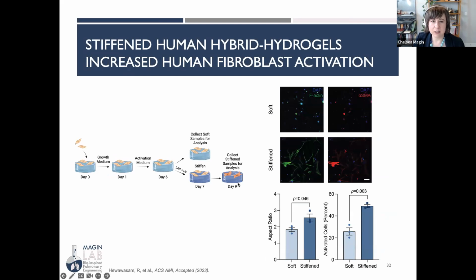So you can see in the stiffened human hybrid hydrogels, human fibroblast activation increased on the stiffened microenvironments. You can see here in staining for F-actin and alpha smooth muscle actin, and also quantified below. The cells increased in aspect ratio when we stiffened the microenvironments, and also increased in activation or expression of that alpha smooth muscle actin. So we're excited. This paper was just accepted at ACS Advanced Materials and Interfaces, and should be out within the next week or so.